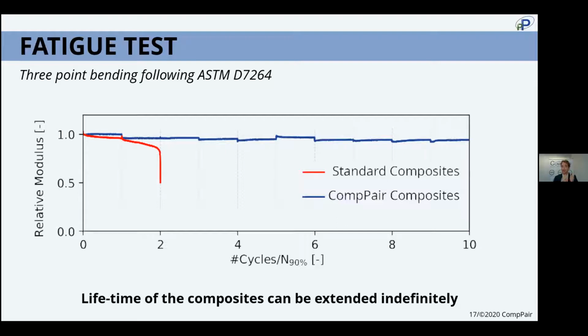And what you see here is a typical modulus on the left for different healing cycles. And what we have done was to take the sample and get some fatigue testing and then see how they can recover damage after they are damaged at a 90% probability of failure. We stopped the test, we healed the samples, we redid the test again, and what you can see is the fact that for standard composites in red, this is failure after 2 cycles. And for CompPair composites, basically, you can highly extend the lifetime of the composites for a lot of time as compared to standard composites.